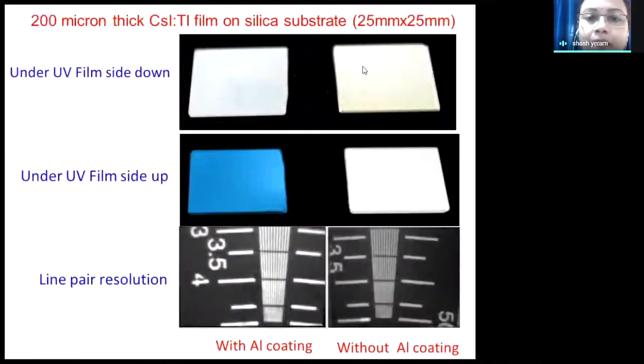These are a few photographs of the cesium iodide that I am showing, a 200 micron thick cesium iodide film on silica quartz substrates which I have made. After deposition we have to do the luminescence studies, and this is the line pair resolution. Line pair resolution is the minimum resolution of lines which it can differentiate. We have been able to achieve around 50 micron line pair resolution. So if you have a fracture in any bone, a hairline fracture of 50 micron or so, where your hair diameter is 100 micron, those kinds of fractures we can detect using our films.